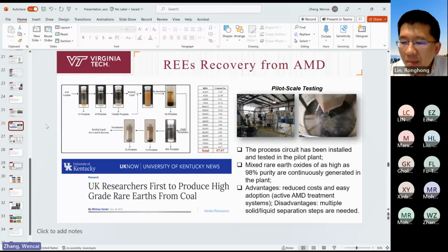I think our overall recovery is higher than 80%. This is because the precipitation pH window of rare earths is very narrow. So basically, you don't have to increase the pH value from 3 to 10 to collect all the rare earths. The majority of rare earths precipitate in a very small pH range window of 5 to 7. So between 5 and 7, you can get almost 100% of rare earths precipitated.